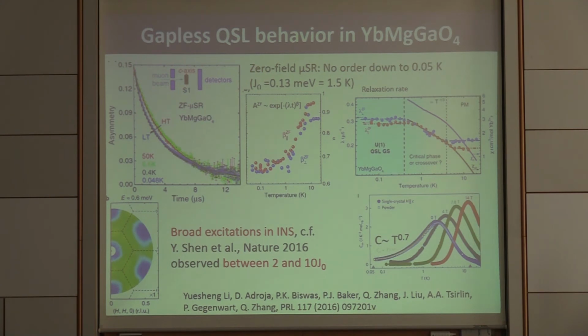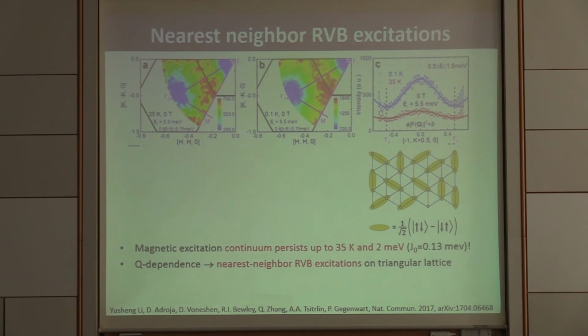In the inelastic neutron scattering, the Oak Ridge group has observed recently a very broad excitation continuum, but remarkably that was measured at quite high energy, although in absolute scale it's very low energy. The problem with that material is that the dominating exchange is very, very small. It's only 0.13 millielectron volt, which corresponds to 1.5 Kelvin. So in the experiment, which here was done at 0.6 millielectron volt, it's already at several times J, where we study the excitations.